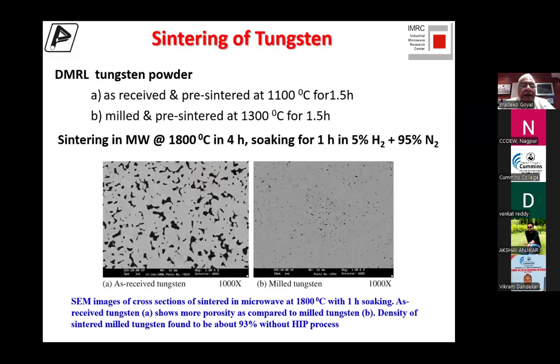One challenging assignment came to us from DMRL in Hyderabad, that they had tungsten powder and they wanted to actually melt it also in some places. And they also gave us the powder to look at how we can make a microstructure better. And here you can clearly see that when we did as received tungsten at 1000x, you see the SEM images of the sintered in microwave at 1800 degrees Celsius with 1 hour soaking. So not only we could go up to 1400 for steel, but for tungsten we went up to 1800 degrees Celsius